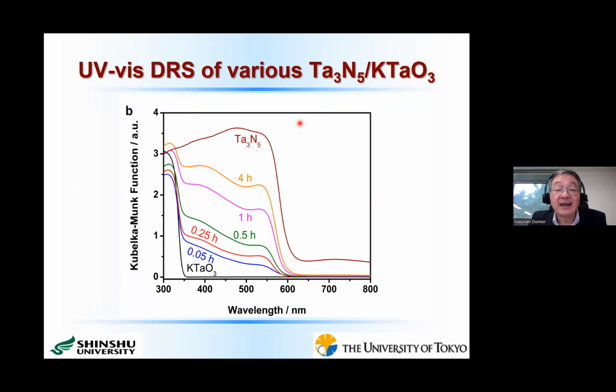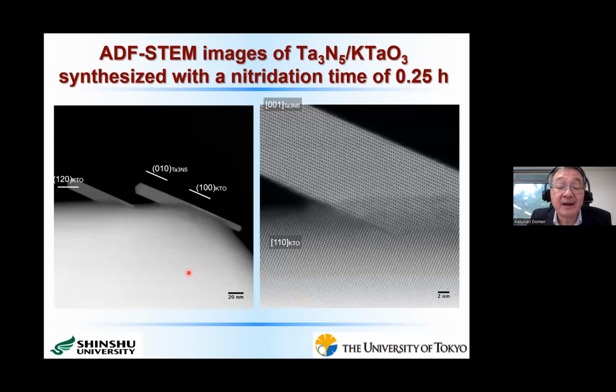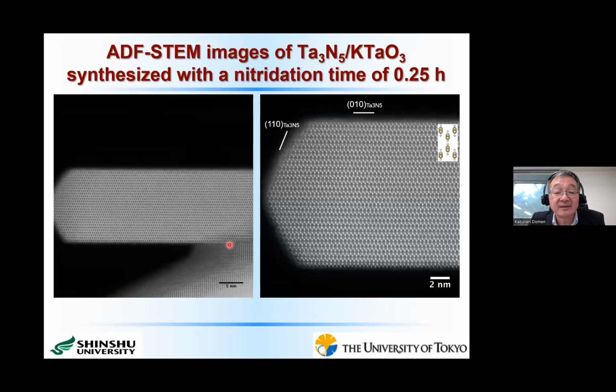If we take UV spectra again, okay, this is potassium tantalate. Then when we started the nitridation, you see that from the very beginning stage, the absorption edge is already extended to 600 nanometers. This seems to indicate that we are directly preparing Ta3N5. To get more clear evidence, we carried out STEM measurement. Okay, this is potassium tantalate. This is a nanorod, which was prepared by the nitridation method. You see, this is a nanorod structure, and this is a completely single crystalline particle. If we look at this figure, up to the uppermost layer, this material is very, very crystallized. And more importantly, from the lattice constant of these materials, this is exactly Ta3N5.